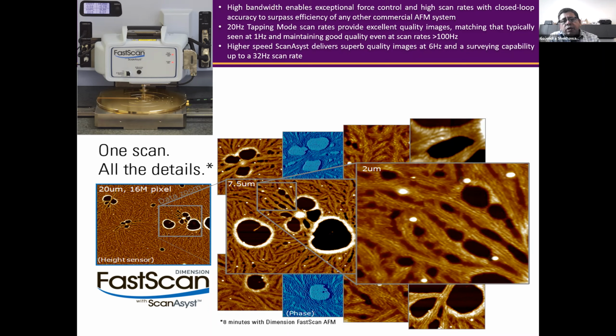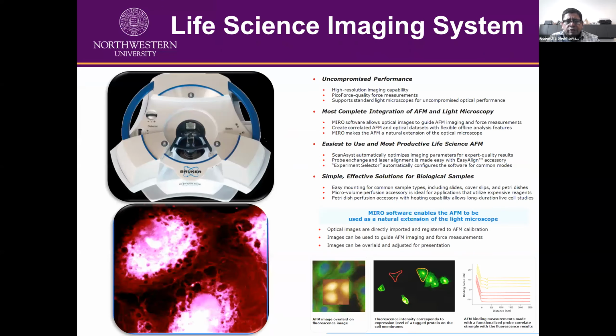But here in our center, we have a high-speed AFM where you can do topographical imaging, peak force tapping, mechanical mapping, and you can have one frame in 1 second. So it's a pretty high-speed AFM. It's pretty popular and fully automated, so you don't need to do a lot of alignments and those things. That system is available here, and people are using it because if you have a large number of samples, you can obviously use these techniques. But this system will not provide you any electrical measurements. Obviously, you have to go to different setups.